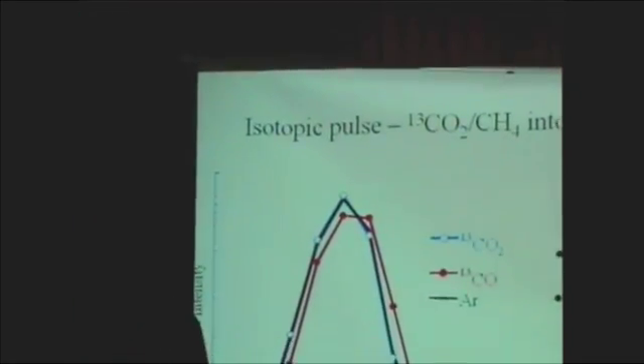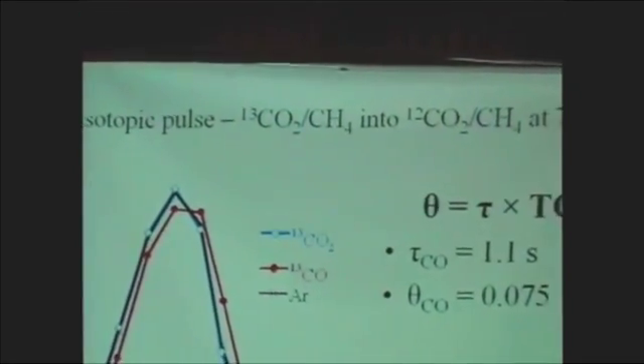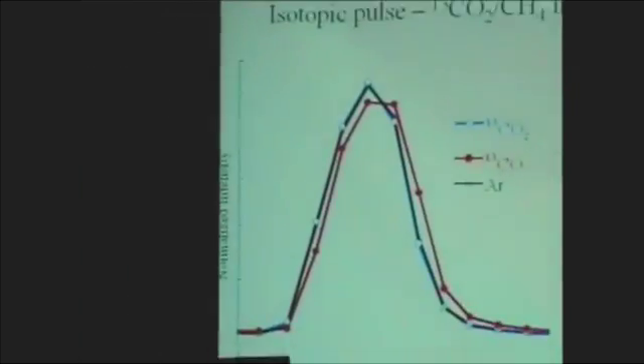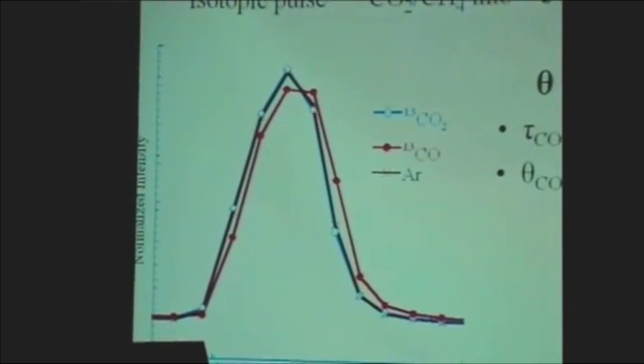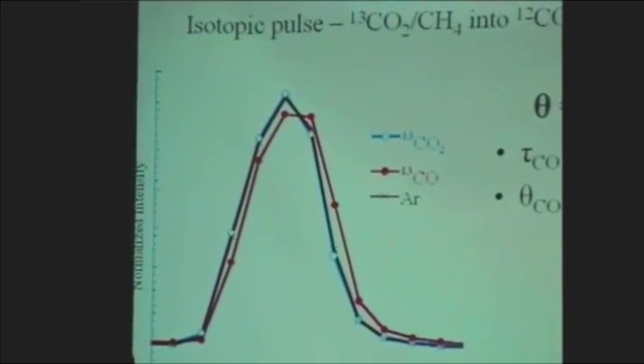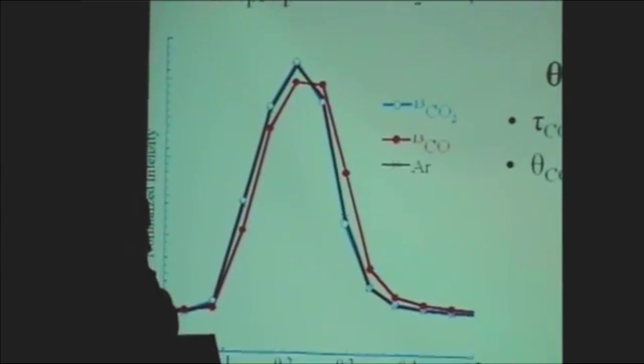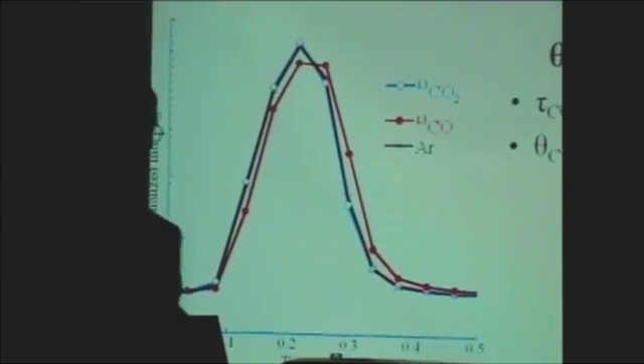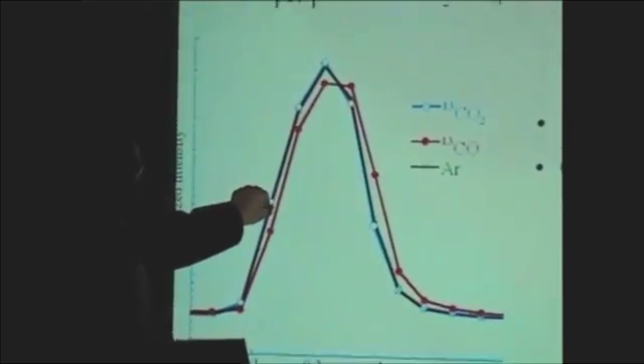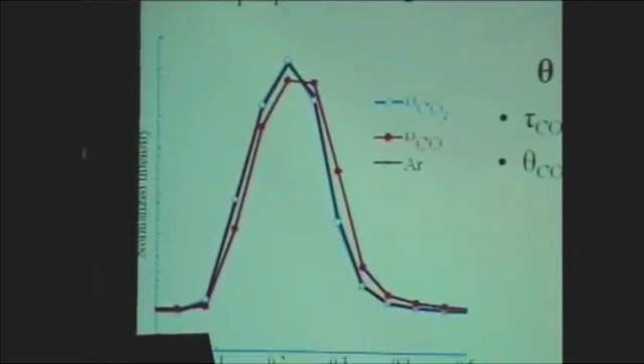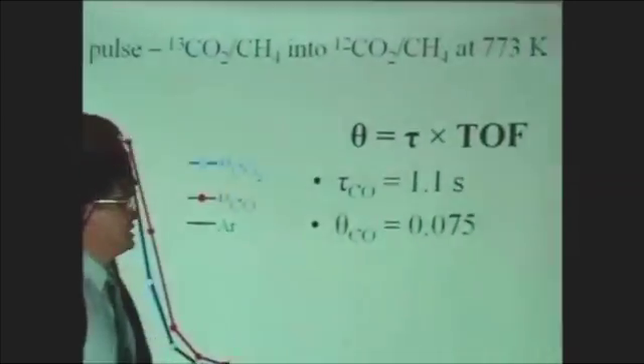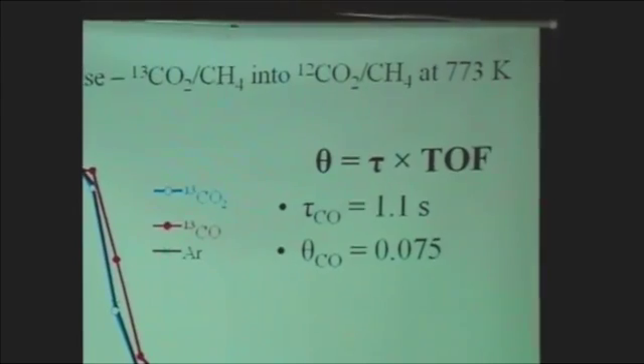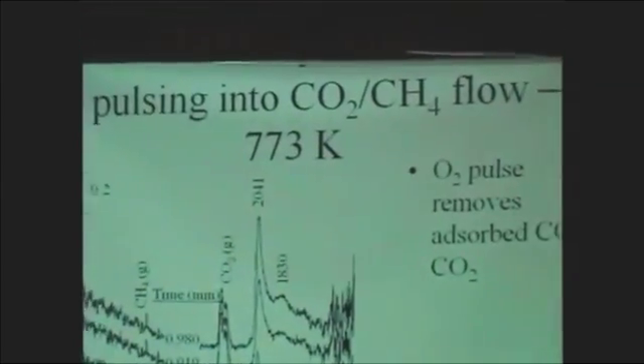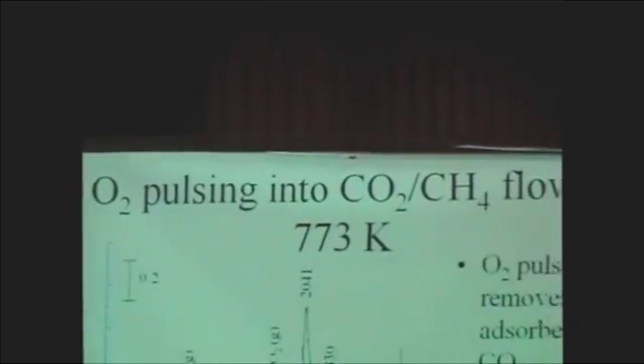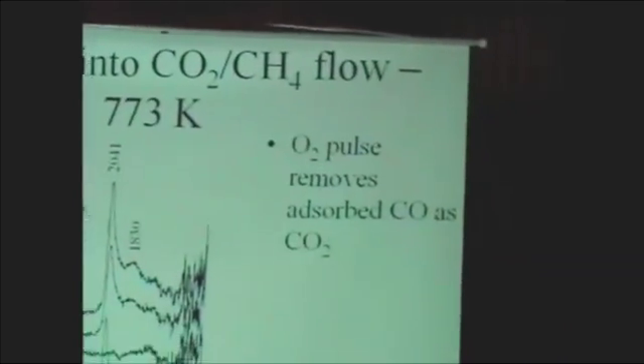We also use the pulse technique. In fact, this pulse technique was developed by Mike 16 or 17 years ago. The reason we like to use the pulse technique is that we use a small amount of isotope, and isotope is quite expensive, so we play with different tricks here. Using the pulse technique, we replace the 13CO2 with the 12CO2, and we can find out this delay. The residence time is about 1.1 seconds. By using this simple first order equation, we can determine how much adsorbed CO is actually on the catalyst surface. So this is simply an exercise to determine the residence time of species on the catalyst surface.